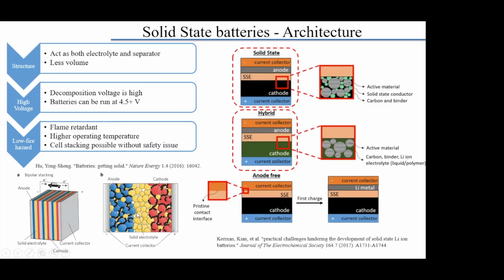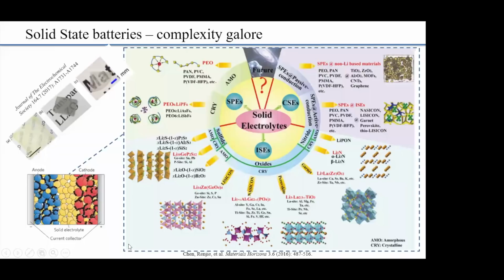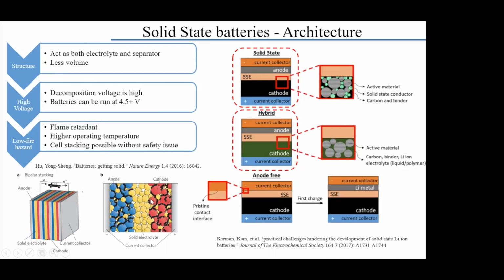And in the previous slide, we looked at the architecture for a typical lithium ion battery. This is a simple architecture for a solid state battery. In the middle, you have particles of solid electrolytes. You have anode on one side, and cathode on the other side. You have to have nice amalgamation, because if you have abrupt interfaces, that's going to lead to terrible performance of the battery. So you see some solid electrolyte particles in the anode and cathode to make it a seamless mixture.